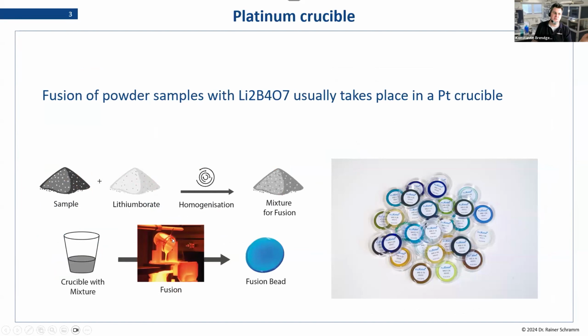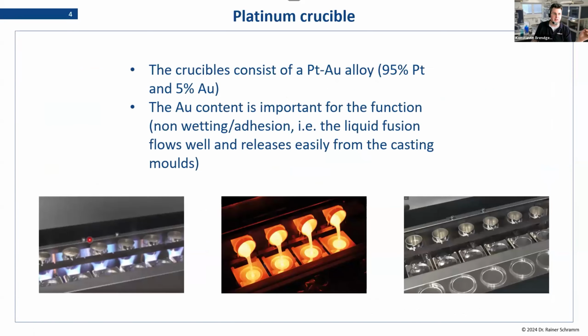And the fusion process, of course, takes place in these machines. And the dishes we are using are mainly platinum. The alloy we are using here is the 95% platinum, 5% gold. There are a lot of other ones, as you have seen in the table before. Also, there are different alloys between platinum and gold. There will be an example later where there is also a 90-10. So if you're looking into other applications other than fusions, there is a lot of information available on the internet regarding those different alloys and what they are best used for. Our topic today is mostly based on this 95-5 alloy, but I think a lot of these experiences that we have from our lab can be transferred to other platinum ware as well.